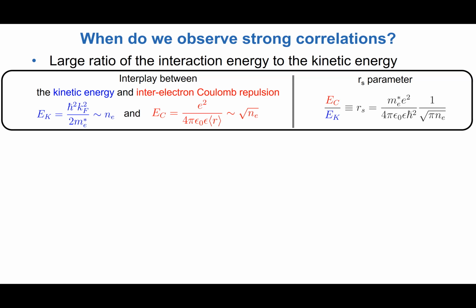Now, if you look at the ratio between the two, which is the so-called r_s parameter, then we see that lower electron densities are favorable for enhancing the scale of interactions as compared to the kinetic energy. Basically, as we reduce the electron density, the interactions become weaker, but the kinetic energy becomes weaker even faster. The net result is that we go into a regime where the properties are dominated by interactions, which then lead to entanglement between the electrons in the system.